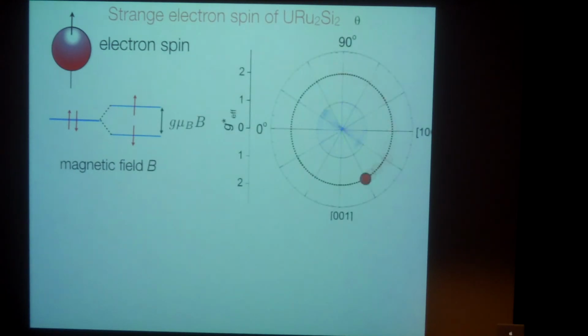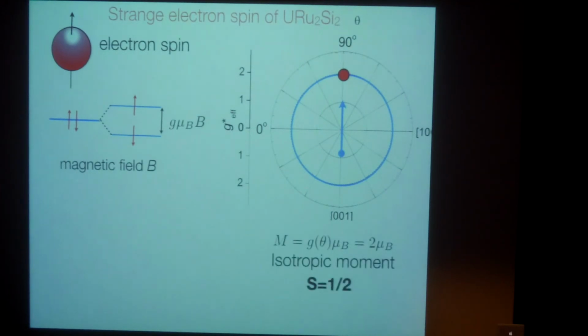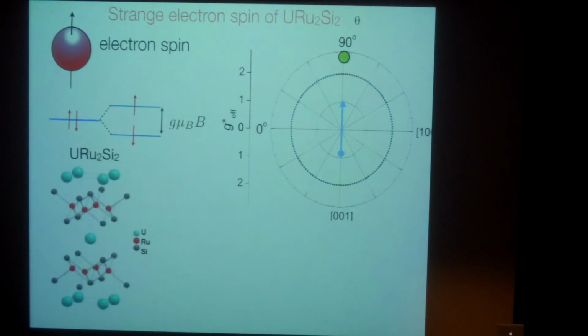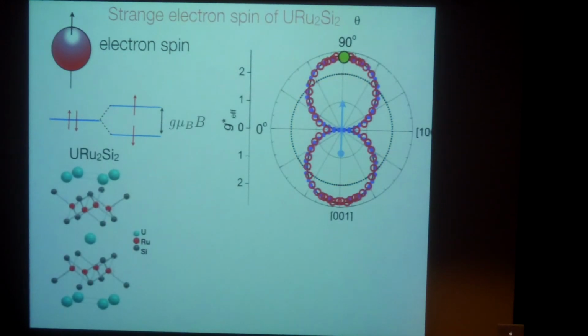And one of the things that's really weird about it is that the G factor, instead of being isotropic like it is in most electronic systems, it's severely Ising-like. You can measure it by various cunning ways. And so an Ising-like G factor in a tetragonal environment is usually a signature of an integer spin. And the uraniums do have an integer spin, but how do the quasiparticles have an integer spin is the real question. And so the idea that we've been playing with is the idea that order parameters can fractionalize.